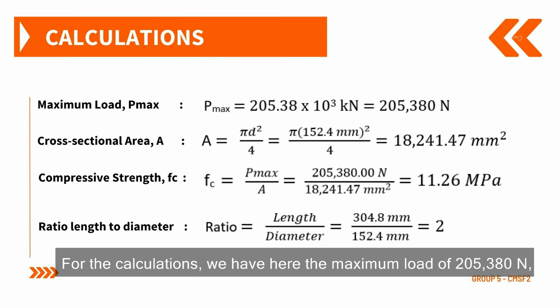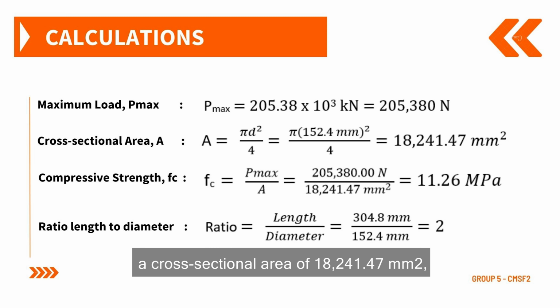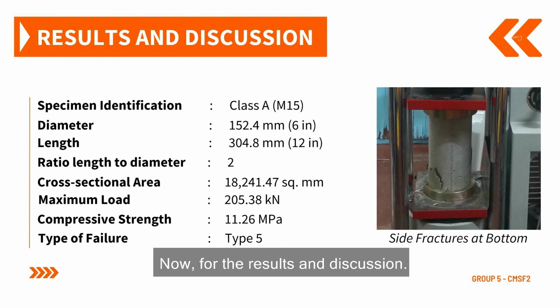For the calculations, we have here the maximum load of 205,380 newtons, a cross-sectional area of 18,241.47 millimeters squared, compressive strength of 11.26 megapascals, and we get 2 for the ratio of length to diameter. Now for the results and discussion.